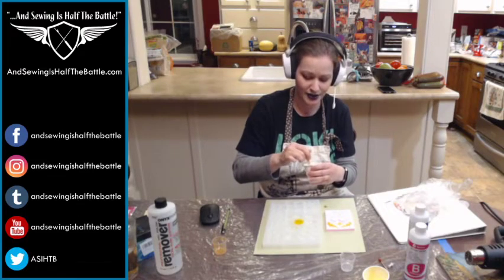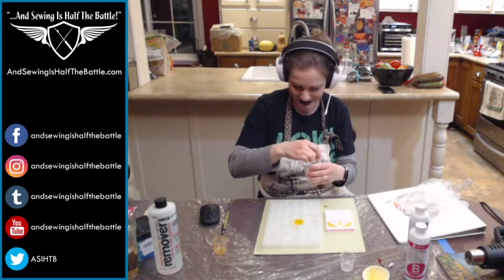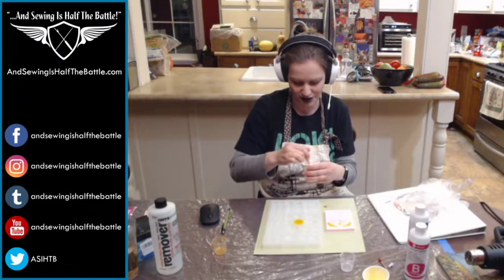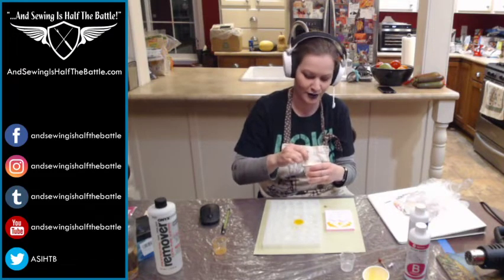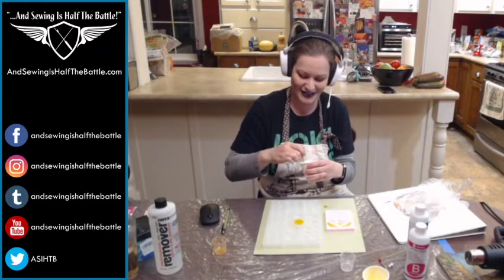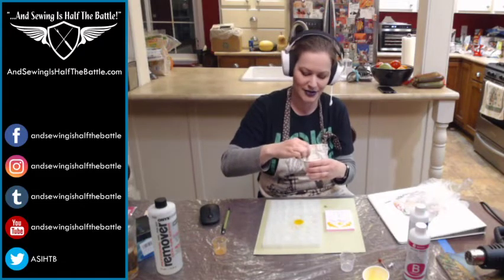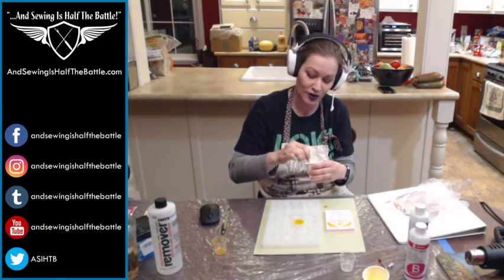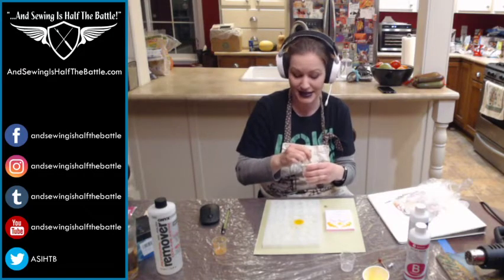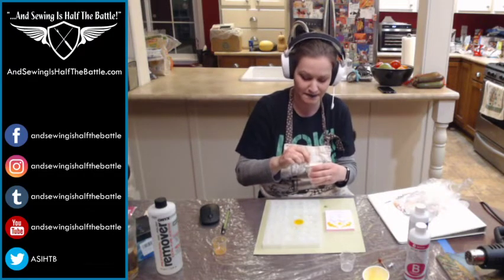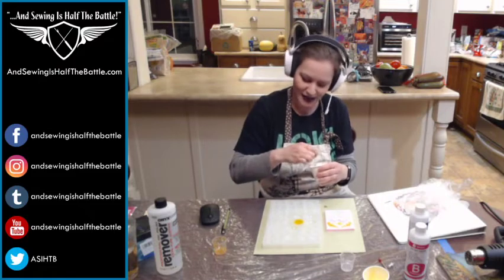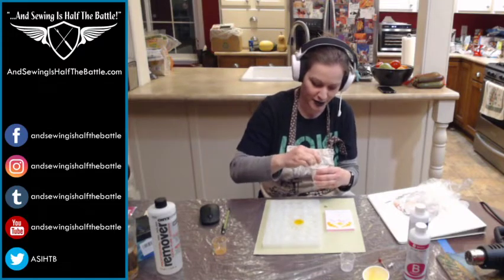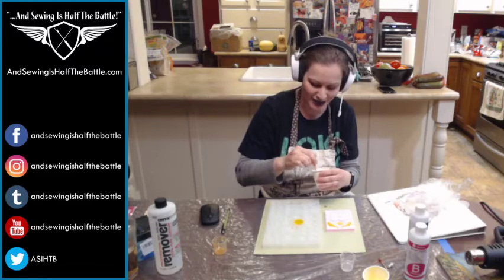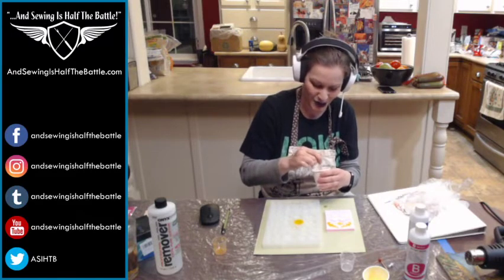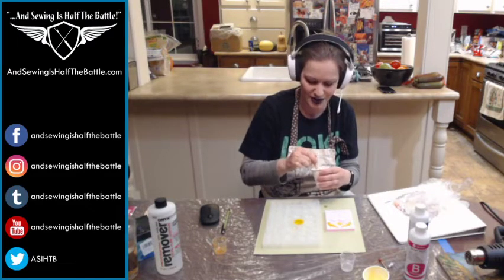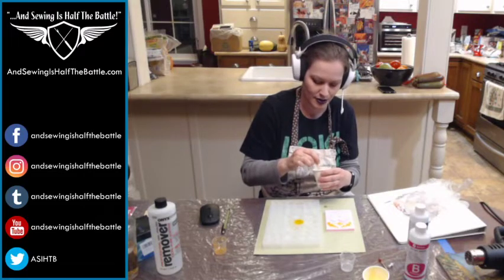I have actually been known to stick resin into a low temperature oven to cure it more quickly, like if it's the night before the con and I didn't make something on time and I'm desperately trying to get something done so I can wear it the next day, and my resin has a 16-hour cure time and I have to wear it in 12 hours. Not that I would ever do that. I totally did that. That was Gen Con a few years ago. But you can actually heat up the surrounding temperature and make your resin cure a little bit faster, just so it doesn't have to compensate with a lower air temperature.